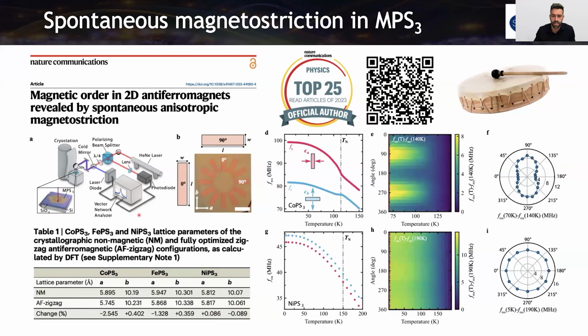And experimentally, they were designing these kind of membranes with the material and exploring how the system behaves when cooling down the system, activating the magnetic long-range order. So in the case of cobalt, this compression of the a-axis is observed here and expansion of the b-axis. This work was published last year in Nature Communications. This is here. And you can observe that in the case of nickel, the evolution is isotropic. So here it is more clear that isotropic distribution, so it's not any effect.